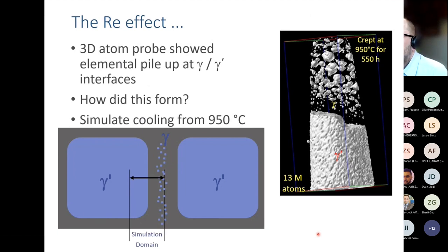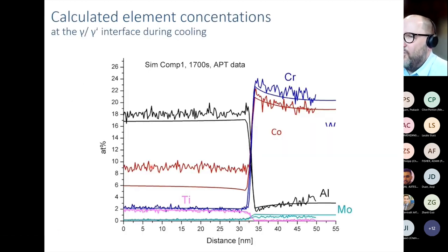Here's some work we've done a few years ago where we tried to rationalize some effects we see in the 3D atom probe. The question here was clearly whether we could rationalize the rhenium pileup at the interface. So we did the simulation again using a phase field model, but only in 1D. Just to cut that story short a little bit, here we have a very quantitative comparison between the concentration profiles we got out of the atom probe, which are the wriggly lines, and the smooth lines representing the results from the phase field simulation.